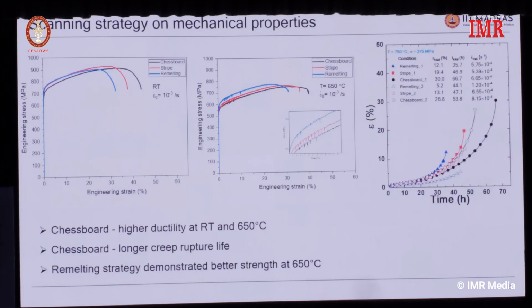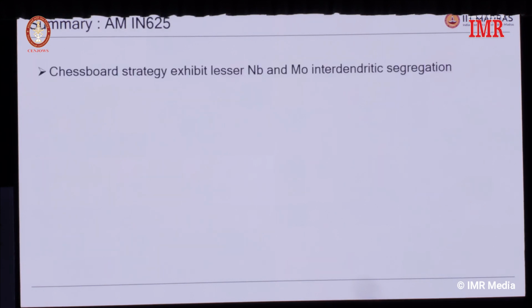Similarly, some of these components have to be qualified for their creep resistance. It means that they have to withstand the time dependent plastic deformation that occurs at high temperatures. So we have to do the testing as well for these materials. We have done the creep testing in our lab. What you can see here is that the black symbols, the black spheres, are for the chessboard, and that gives a better creep rupture life. So though you have a higher strength in some of the other scanning strategies, the one giving the better creep rupture life is the chessboard scanning strategy.